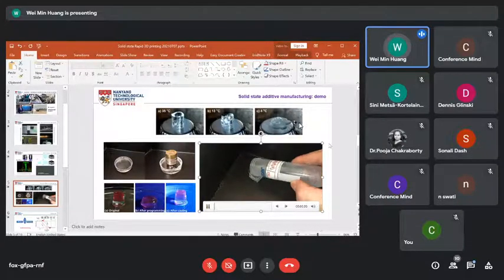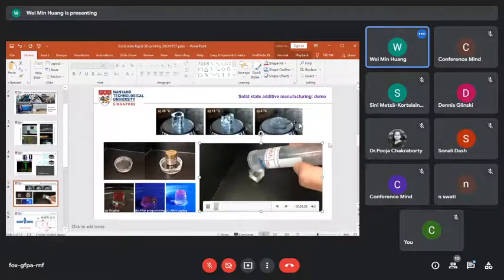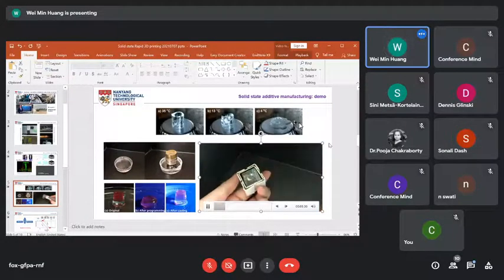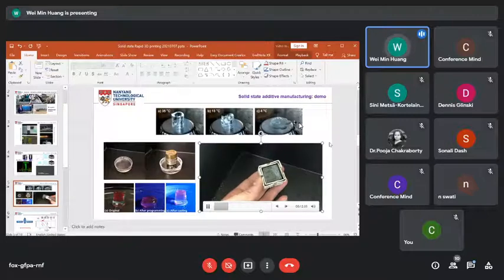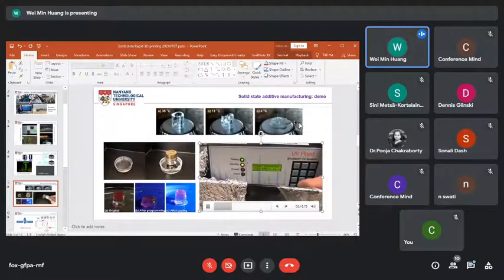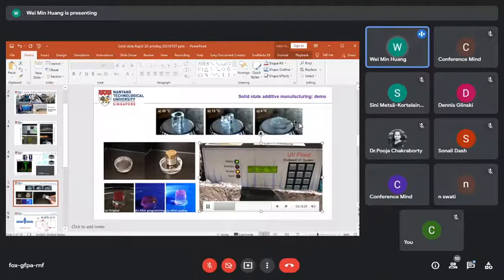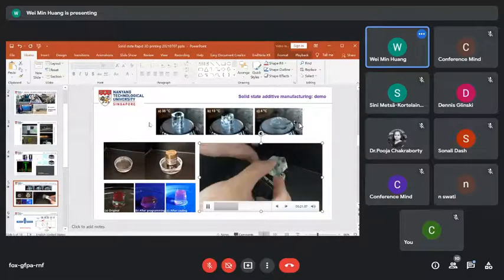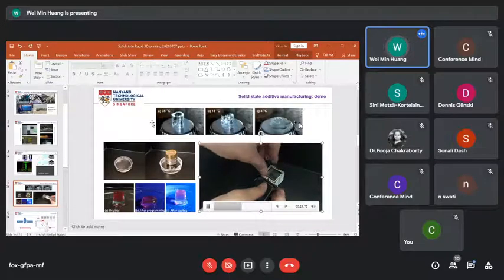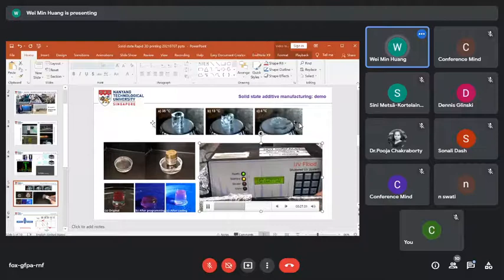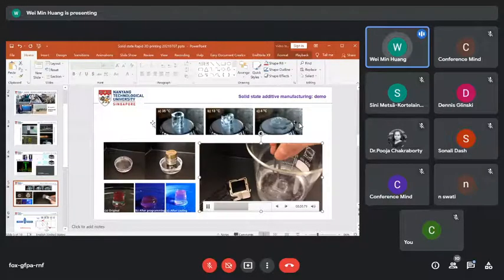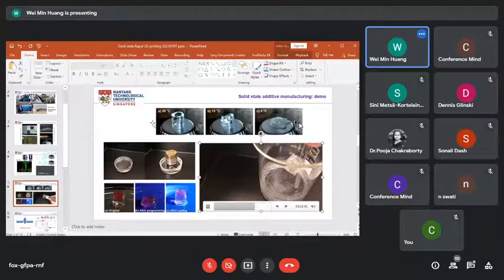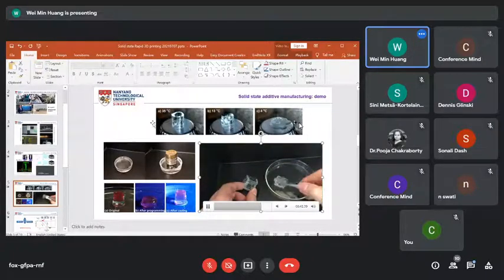So here we have a video to demonstrate this concept. I hope that you can see this, although the size is relatively small. So it's a solid. It's strong enough. We can place a few coins on top of it without sinking. Now we can turn that by 90 degrees after first cross-linking. Use the same mask, and we use UV to shine on that for 1 minute. And the result of that is solid. We need to cool it in ice water and then take it out. So here we go.